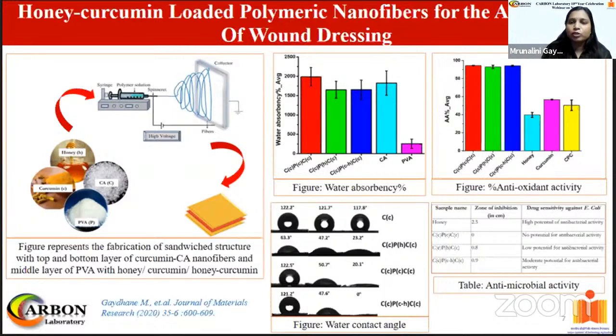healing biomaterial. Based on the mutual solubility of drugs and polymer, the sandwiched mats were fabricated, comprising top and bottom layers of curcumin-loaded cellulose acetate nanofibers and a middle layer of polyvinyl alcohol loaded with either honey or curcumin and both the drugs together. The characterization infers that the selection of polymers in the multi-layered assembly assisted in quick absorption of wound exudate and high water absorbency. Compared to the pure components, the synergistic activity of honey and curcumin further enhanced the antioxidant activity up to 93% and exhibited moderate potential to eradicate E. coli infection. Thus, layered assembly can be used to deliver multiple mutually insoluble drugs to enhance the therapeutic index.